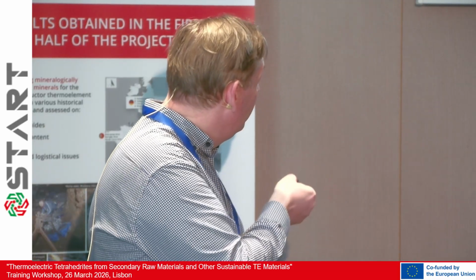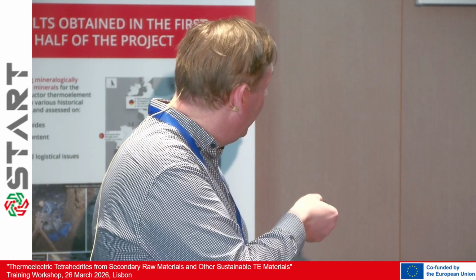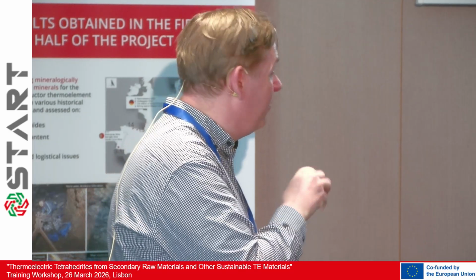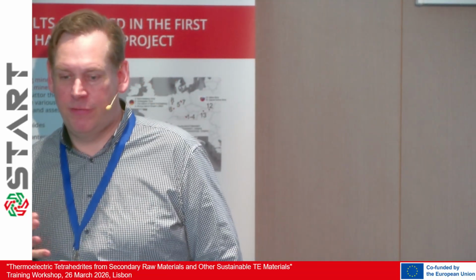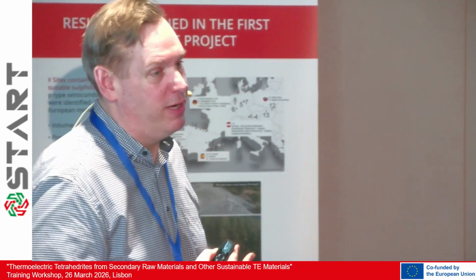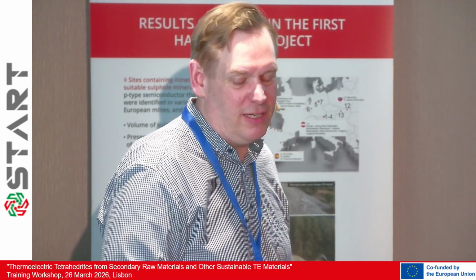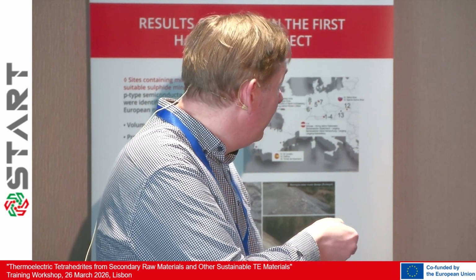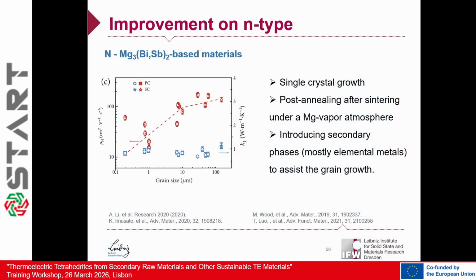Another strategy to improve it is to play a bit with the doping and the crystal structure. And this is very different: the magnesium material behaves very differently compared to bismuth telluride. With bismuth telluride, you can make very tiny grains and you have a very low thermal conductivity. This works quite nicely. Here you have to apply a very different strategy. Here you like to have very large grains because the mobility of the charge carrier is strongly affected by the grain size. So when you come down to, let's say, grains in the range of 100 micrometer, you have mobilities of the charge carrier which are very close to single crystals.